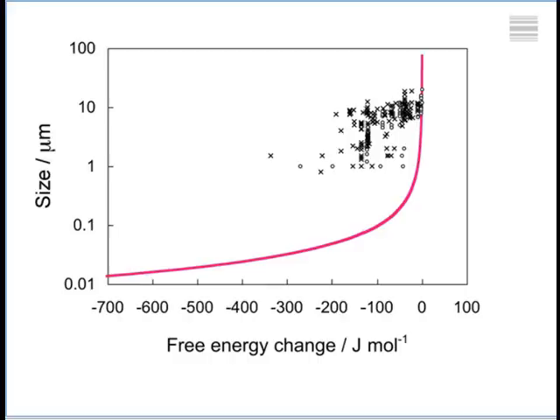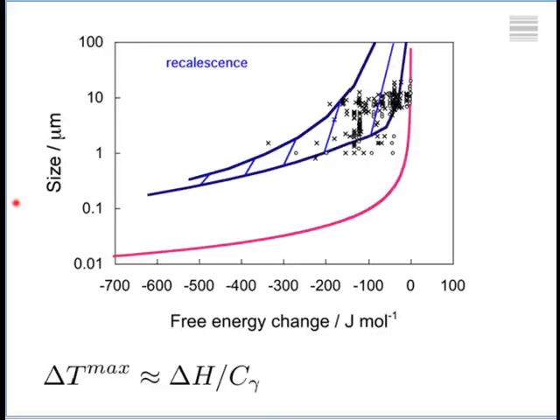The problem is as follows, that as I increase the undercooling at which ferrite forms, heat is released in the steel. Okay? So this is something called recalescence. The heat of transformation actually warms up the steel. And when I take that into account, my theoretical limit actually changes to something which is more realistic here. And what it tells me is that by thermomechanical processing, as long as we want to make large quantities of steel, you are not going to be able to produce a grain size which is much finer than 1 micrometer. Okay? So that is the reason why we are stuck at approximately 1 micrometer as a fine grain size when it comes to bulk production of large quantities of steel.